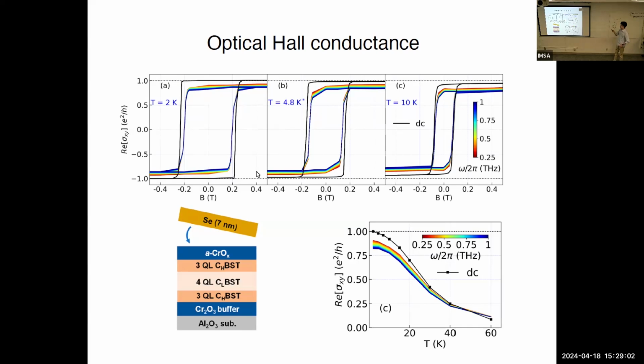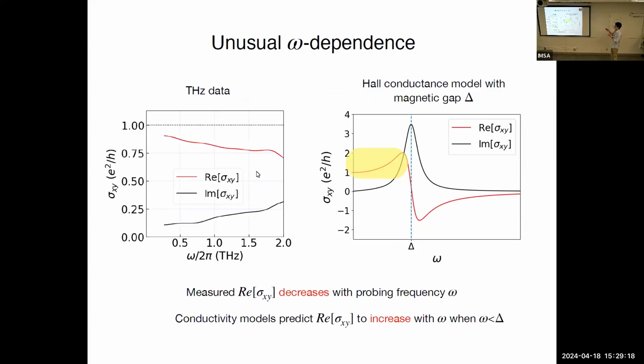Before that, I also want to show this. Here the frequency dependence is shown in the color code, but if I plot it as a function of frequency, I'm showing both the real and imaginary parts of the Hall conductance. The real part corresponds to the non-dissipative part of the conductivity, and the imaginary part is the dissipative part. Since we are measuring with a time domain technique, we can get both. But the real part is the one which is going to e squared over h, as in the case of DC Hall conductance.